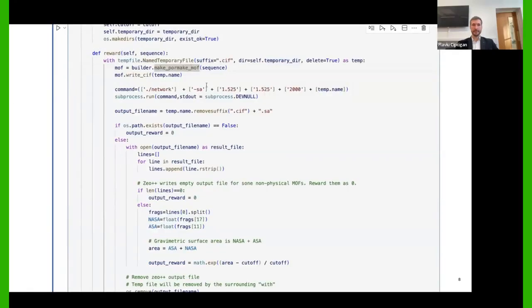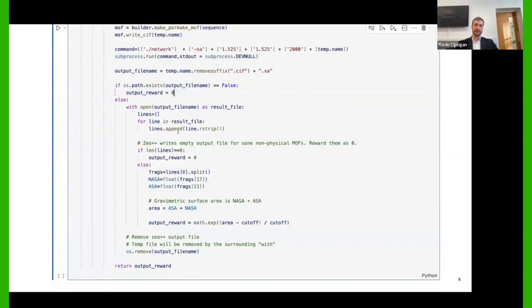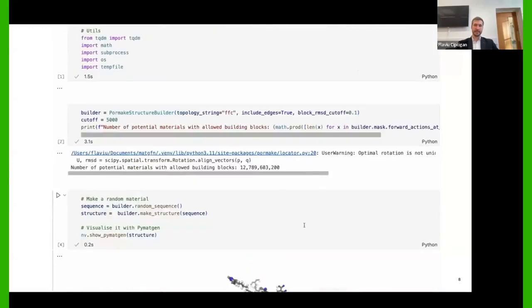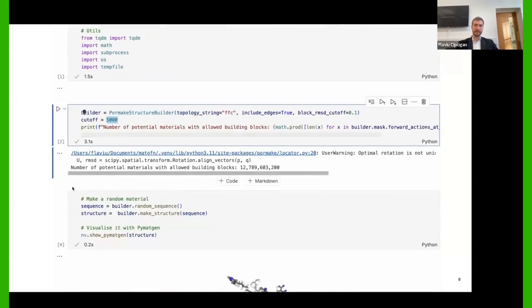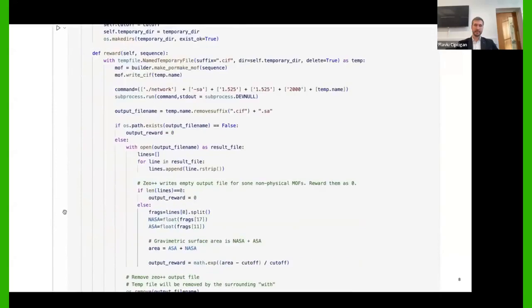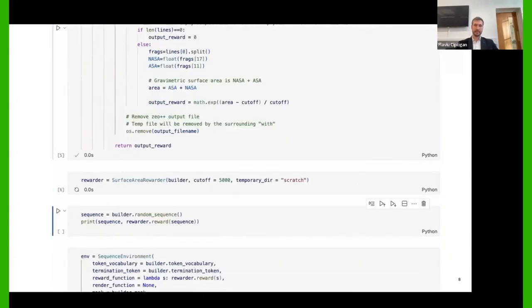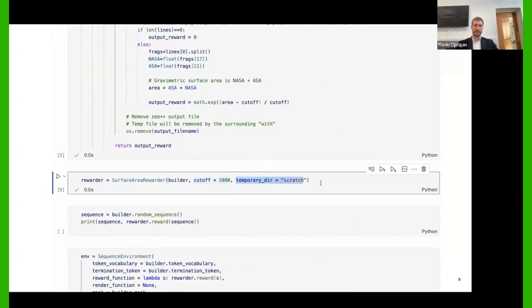The way that this reward is created is as follows. We get a sequence of building blocks and we write that sequence as a CIF file in a temporary folder. We then run the network command. This is the Zeo++ software that calculates the accessible surface area. Then we read the output of that software, we get the total surface area, and we create a reward. That reward is the total surface area minus a cutoff divided by the cutoff. Here, the cutoff is 5,000 square meters per gram of material. Okay. Once we have this reward class, we instantiate it. So cutoff equals 5,000, temporary dir equals scratch.